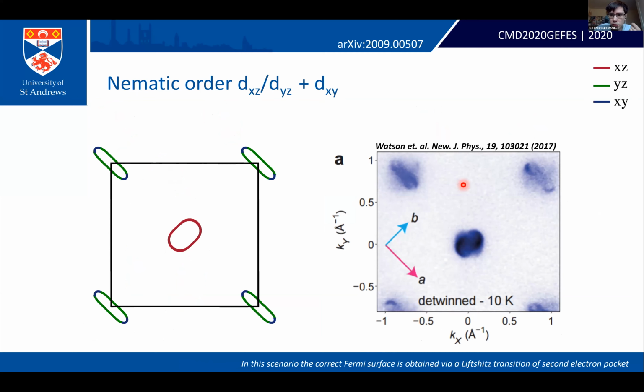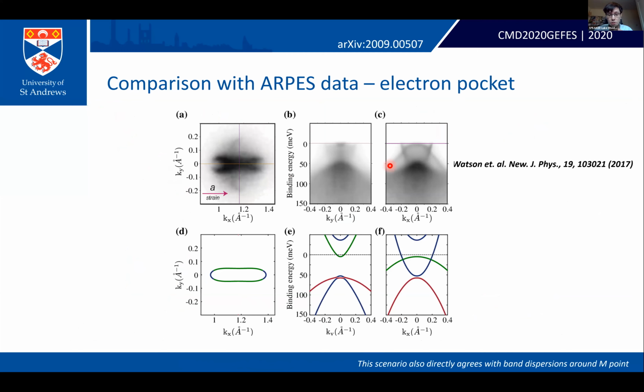And that can reproduce the experimental data, not only as a function of the Fermi surface, but also as a function of binding energy. Here we have some ARPES data of the electron pocket around the M point of a detwinned crystal. This is the Fermi surface of the electron pocket, and these here are cuts along the Y and X direction as a function of binding energy. And this is the first time that such good agreement can be obtained within a model of iron selenide. And it's all because we've included nematicity within this dxy channel.